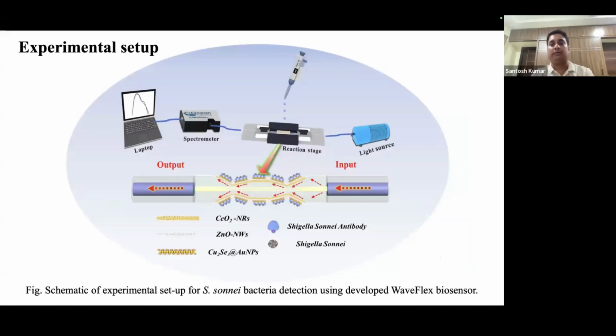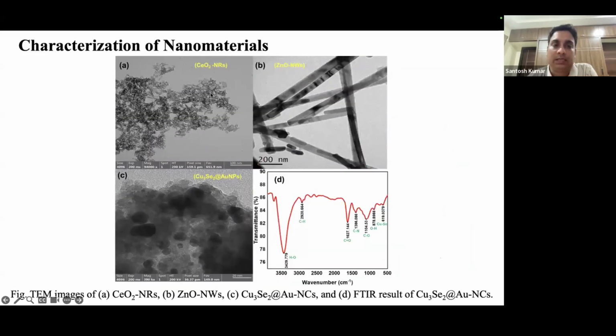I have already discussed that we have used the tungsten halogen light source and a spectrometer, and in this case we can just change the solution, and after that we can wash the fiber probe with PBS, and we can reuse it multiple times. Okay, so here in this case we have used the cerium oxide nanorod, and we can see it easily, and this is the zinc oxide nanowire, and this is the copper selenium and gold nanoparticle, and this one is the FTIR result that confirms the copper, selenium, and gold nanoparticles.